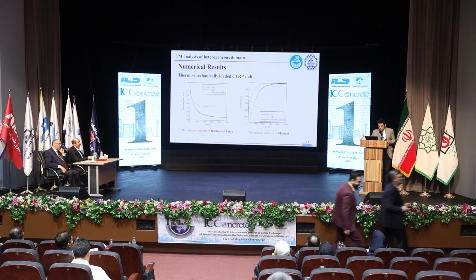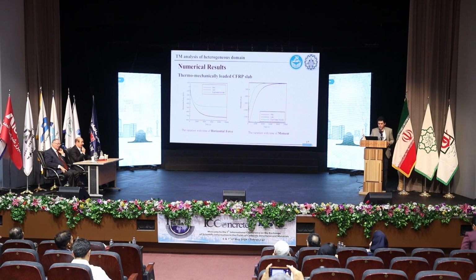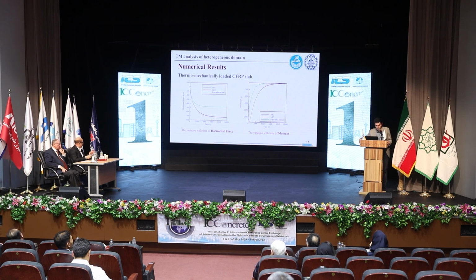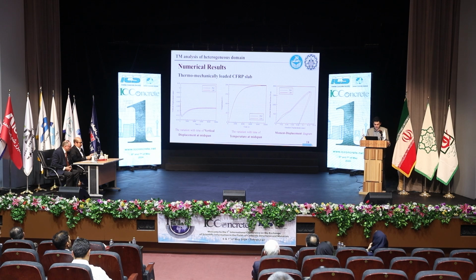Now, you see the results of our simulation in comparison to the conventional equivalent models, which are relevant in practical problems. You see that our multi-scale analysis differs significantly from the equivalent models, which shows that these equivalent models cannot capture the real and true behavior of these kinds of structures. And these are the variation with time of horizontal force at the support and the moment at the support. And also other results: you can see vertical displacement of the middle of the slab, temperature, and also moment versus the displacement at the middle of the slab.